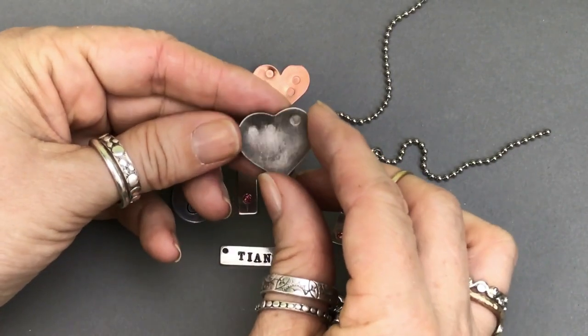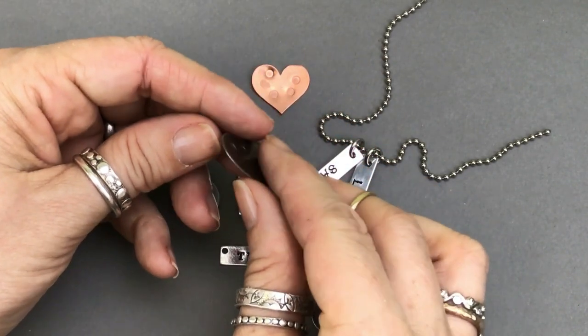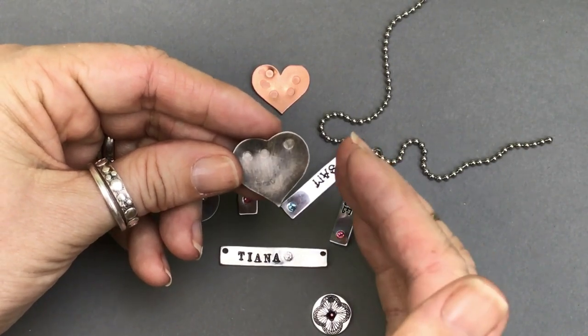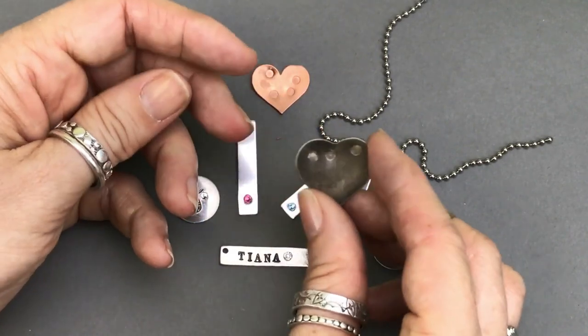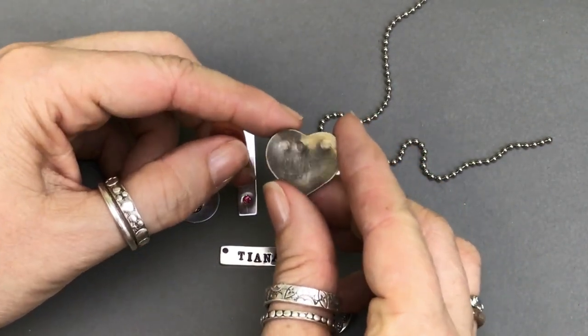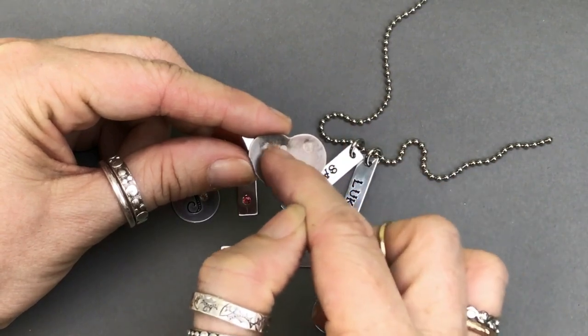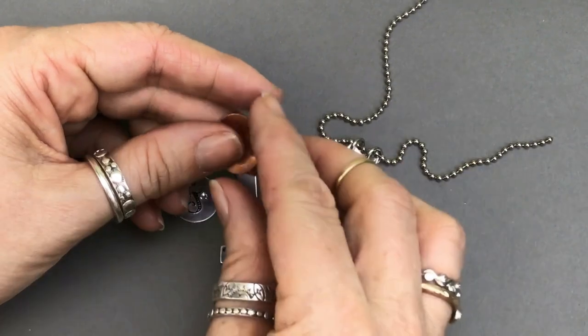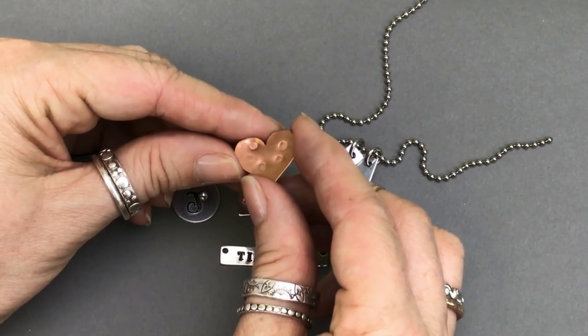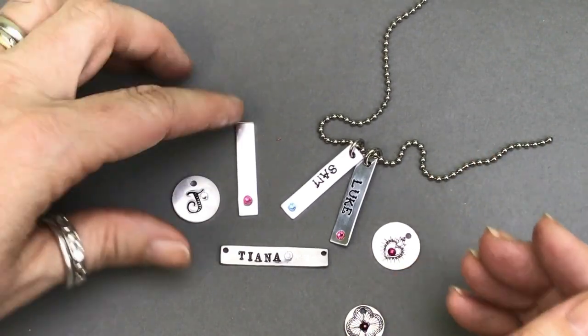For example, this is nickel — I was really pushing because this is 24 gauge. I originally thought this tool would not work on 24 gauge. Think about it this way: 24 gauge is really, really thin, so you have to push the tool in enough to make a nice indentation with a nice edge to hold the crystal, but if it's super thin, that space in the metal just doesn't exist. My honest opinion is it's not great on 24 gauge, but you can do it. Nickel is a really hard metal, so I tried to make an indentation, it didn't go great, then I annealed the metal to soften it and was able to get a better one — but you can see it pushed through on the back. Same on the copper one — I didn't have to anneal it since it's softer. I would recommend this tool for 22 gauge and thicker, with 18 gauge being great.